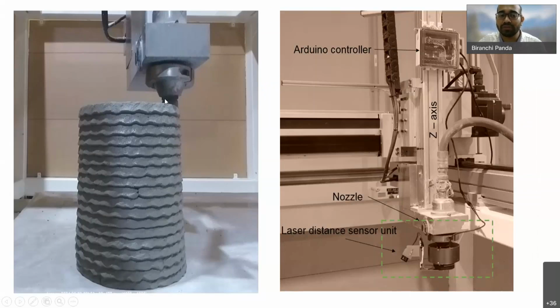So to avoid the deformation, we added a distance sensor, which continuously monitors the distance from the top. If there is any deformation during the process, we get a feedback, and accordingly the process parameters are adjusted so that the deformation can be minimized. So this is how we have also improved the process to minimize the deformation.